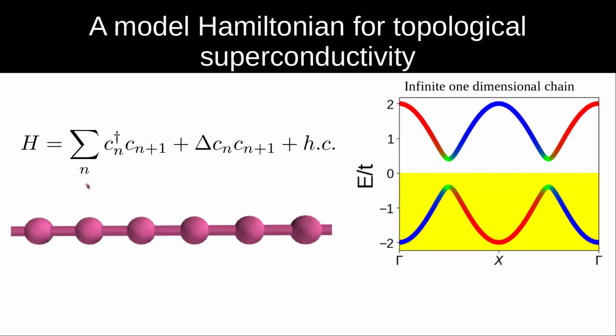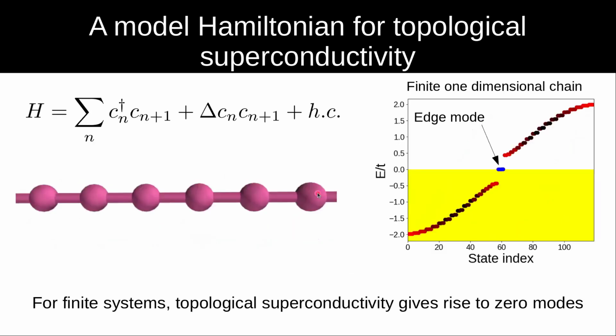And so if you now take this Hamiltonian and do some, let's say, brute force diagonalization, first in a periodic system, what you observe is that, of course, this delta opens up a gap in reciprocal space, and this gap is the superconducting order. So in a periodic system, you have a band structure that shows a gap, and this band structure actually has a finite topological invariant. It has a finite Zak phase.